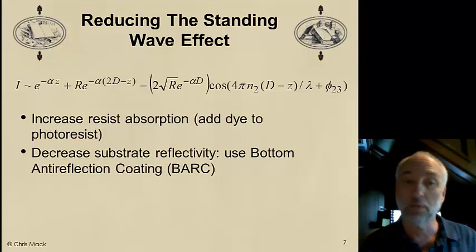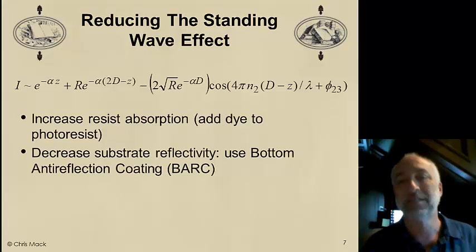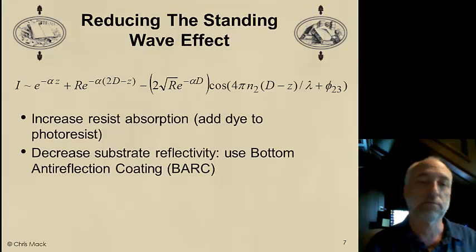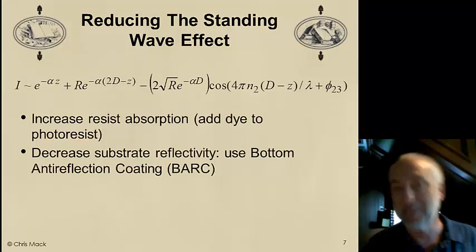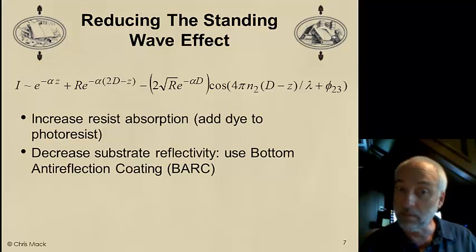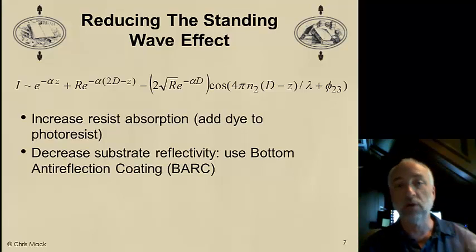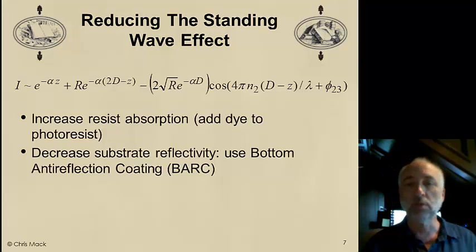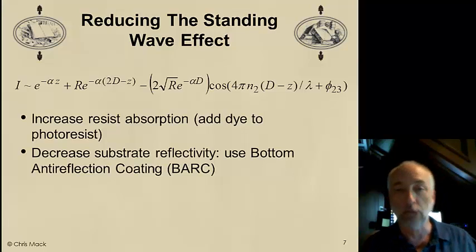And then, of course, we do lithography on metals as well. Very reflective materials sometimes. If I were to just take some black paint and coat the wafer, my reflectivity would go down dramatically. Of course, black paint doesn't sell for as much as anti-reflective coatings, so we don't call it black paint. In fact, it's much more sophisticated than just black paint. Black paint would be absorbing, but we also want to match the refractive index and do what we can to absolutely minimize the value of R more than we could with just absorption in an underlying layer.